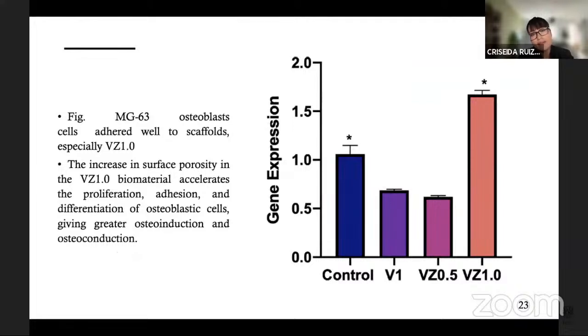The scaffolds were evaluated in vitro with MG63 osteoblasts. The cell adhesion and the effect of the porosity of the scaffold is analyzed, and the sample with the higher zirconia content accelerates the proliferation, adhesion, and differentiation of the osteoblasts, resulting in a better osteoconduction and osteoinduction.